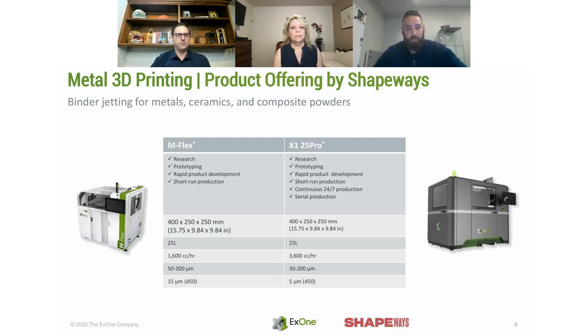The 25 Pro does have the capability to print powders that the M-Flex was not able to print. We upgraded the machine to have what we call an ACT system — an advanced compaction system that allows you to print fine powders. The M-Flex can print down to 15 micron, but the 25 Pro can print down to 5 micron powders. We decided as a business not to add additives to the powder — we want to pull materials right off the shelves to make the consumable product line easier for customers.